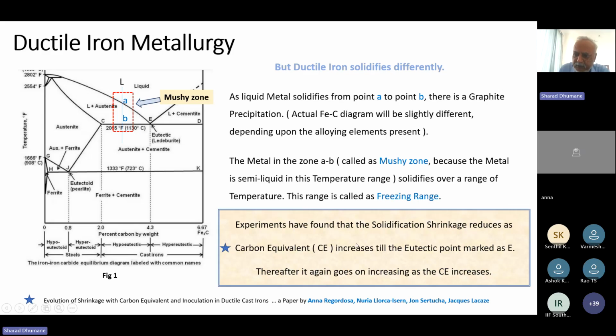This experimental data says that as we move in carbon equivalent towards 4.3, the solidification shrinkage decreases. But after this point, it increases again. You can see the freezing range: as we move from this point to this point, it is decreasing, but from here onwards, it increases again. So we can consider that as the freezing range decreases, the solidification shrinkage decreases, and as the freezing range increases, the solidification shrinkage increases. Okay? Simple.